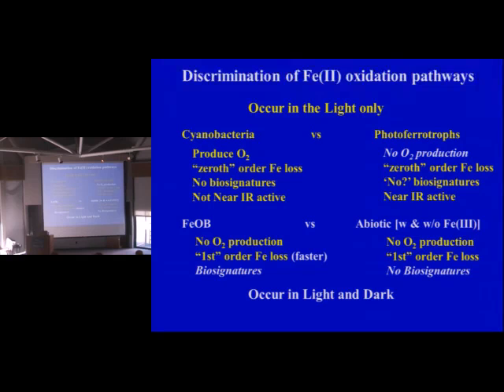I thought the manganese in your system was always in the Mn2 stage. Yes, but I'm saying it was transient, so you wouldn't have seen it. But if I had MnO2 present, and there was no oxygen available, and I would see the iron 2 go down and the manganese 2 increase, I could then indicate that manganese dioxide might have been the oxidant for iron in that case. But we didn't see that kind of condition.